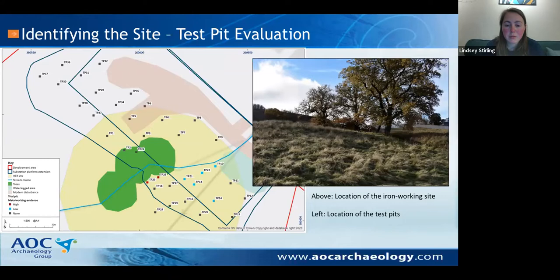And both of these pits contained a really dark black deposit below the topsoil. I think one of them was over half a meter deep. It was really, really rich in charcoal and iron slag, and we were also starting to find pieces of burnt clay. So from this, we were able to identify a much more specific area for our investigations of the ironworking site.